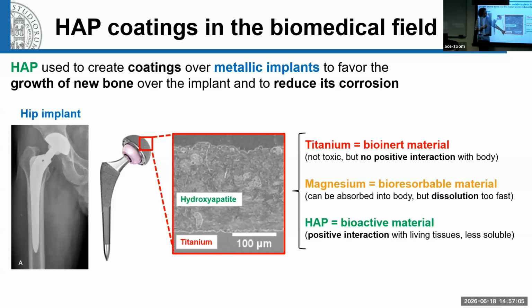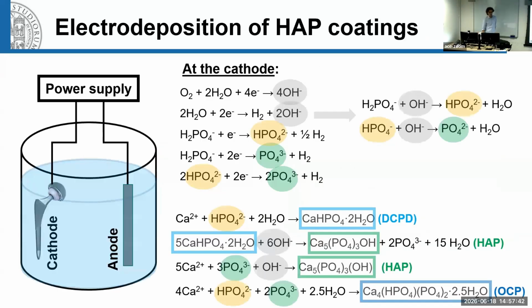Whereas if you use the titanium alone, this is a bio-inert material. It means that it's not toxic to our body, but our body doesn't recognize it as something, let's say, friendly. So there's no formation of a good adhesion between the metal and the bones. So there is some problem, some limitation. By forming this hydroxyapatite layer over titanium, it's possible to make the implant much more friendly, let's say, to the human body. How do you form these hydroxyapatite layers over titanium?